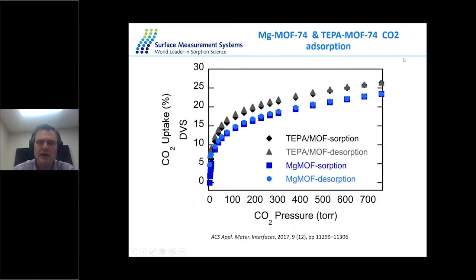differences in adsorption capacity. Here we look at the adsorption isotherms up to 1 bar for these two MOFs. So what you can see here, the adsorption capacity of MOF-74 is slightly lower compared to the functionalized MOF-74. The adsorption of MOF-74 is blue circles and blue squares, which is the MOF-74 adsorption capacity up to 1 bar for CO2. And the functionalized MOF is black triangles and black rectangular boxes. So what you can see is slight differences.